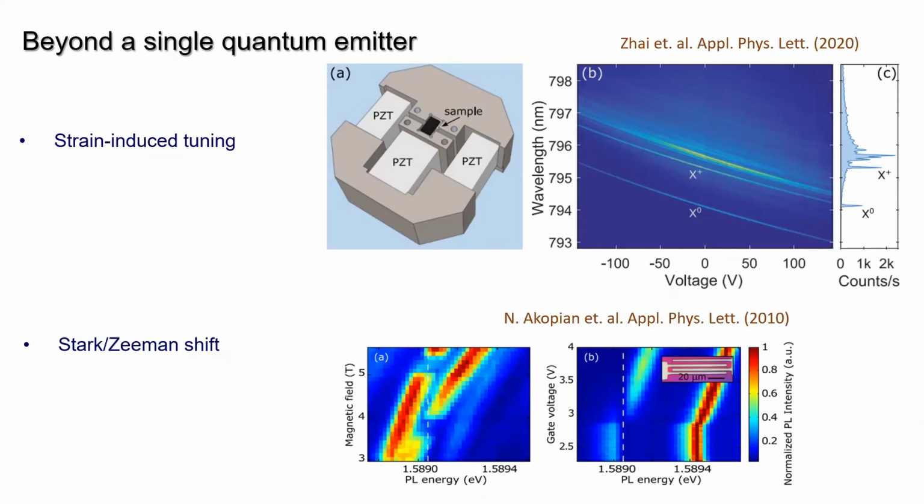But now, if you want to make a circuit, you still need to have talking between these molecules, right? And the problem with anything that's solid state, dibenzoterrylene included, is inhomogeneous broadening. That means even if the peaks are narrow, they're all different from each other. Any kind of strain, imperfection, or location of the molecule is going to move the resonant frequency. And when we're making a quantum system, everything needs to be mode matched. So you need all your molecules in the system to have exactly the same frequency.